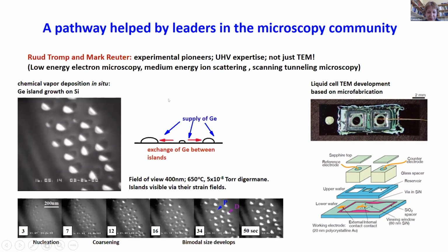So this is clearly a process of Ostwald ripening where we can exchange. So germanium comes down from the gas phase, supplied as digermane. It lands on the surface. It diffuses across the surface and it joins an island, but it can also leave an island, and so the smaller ones with higher energy per atom disappear at the expense. You know, the material goes to join onto the larger ones.